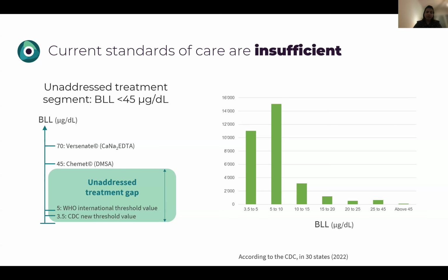So going back to what we know about those standards of care, while the WHO defines a threshold from which an intervention needs to take place as 5 microgram per deciliter, and the CDC reduced this value about 4 years ago to 3.5, in reality, the 2 standards of care are proved to be used at much more elevated levels: 45 microgram per deciliter in the case of DMSA or Chemet, and 70 in the case of EDTA or Versenate.